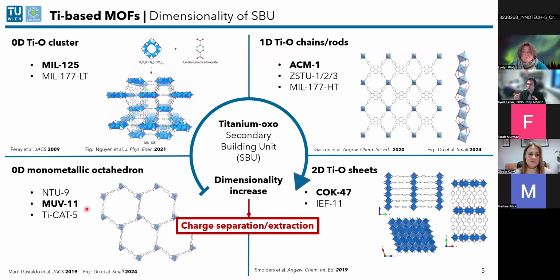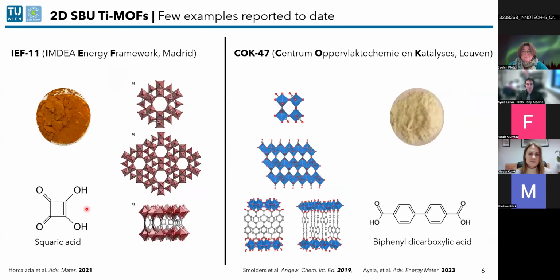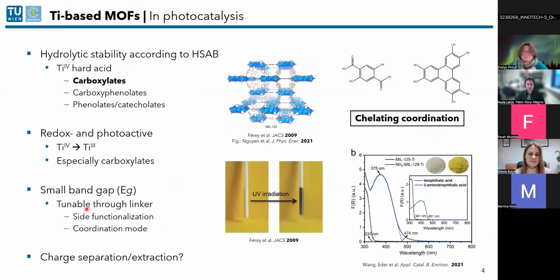But when you have this kind of coordination, the problem is that you lose the effect of titanium. So you don't have this photocharging, you don't have the titanium 4 to titanium 3. So it's all a balance somehow. In my experience, the carboxylates are better for separating these charges, although maybe they might not have the narrowest band gap. So maybe that answers a little bit the first question. Thank you so much.